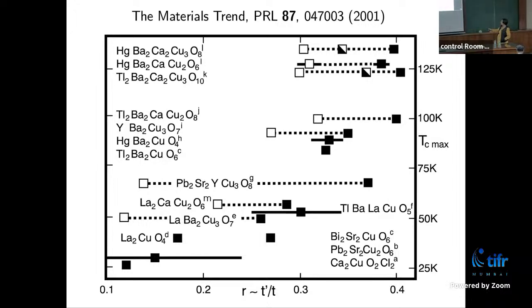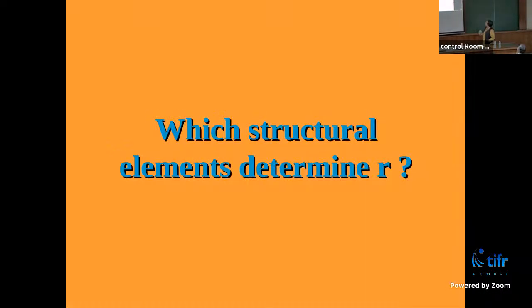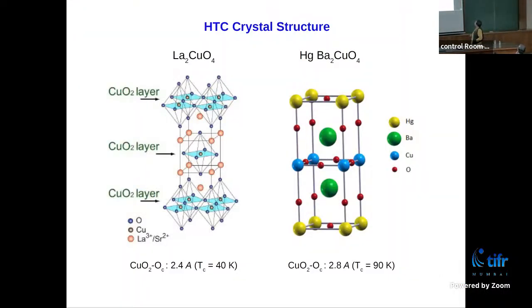If you just follow the black symbols, I will not explain the other symbols for the sake of time, you do find a kind of correlation between this R parameter and TC, not for one or two compounds, but for multiple sets of compounds. Well and good. What is the structural element that determines this TC? There must be either chemistry or structure. This is the high TC crystal structure, well known to many of you. You have a copper oxygen layer, and you have lanthanum or mercury or barium. But most important for us is the oxygen along the C direction, out of plane. That oxygen is known as apical oxygen.